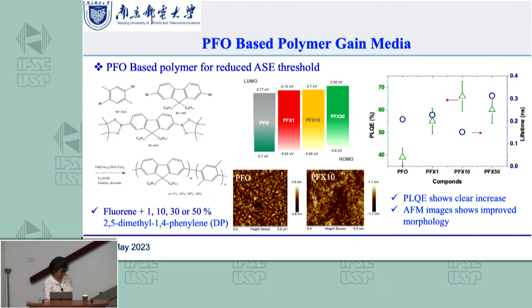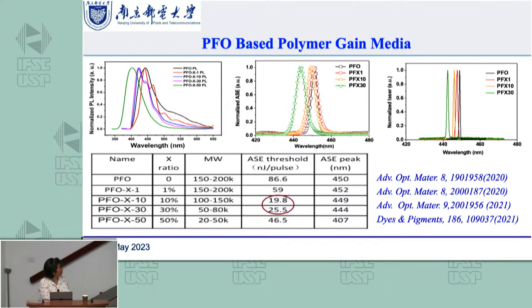So we start with the PFO, just add a side chain. With this side chain, we found the HOMO-LUMO level can be tuned. And also, compared with the morphology, we think it can be improved. In that way, the quantum efficiency also increased a little bit. By this way, we found it's possible to reduce the laser threshold.